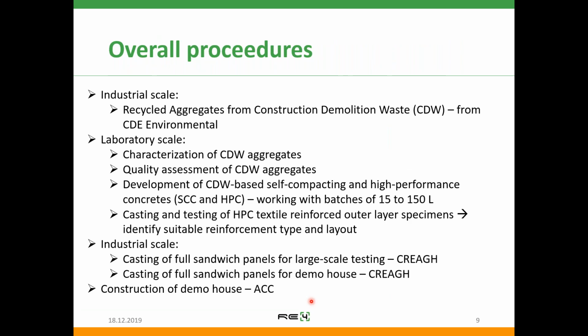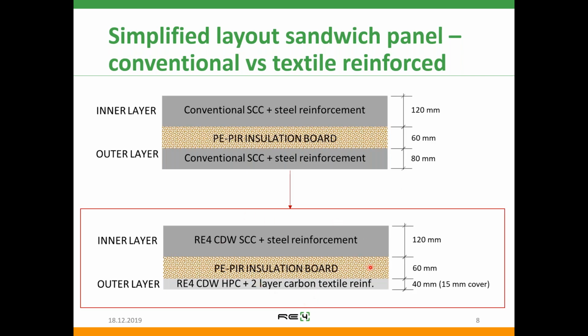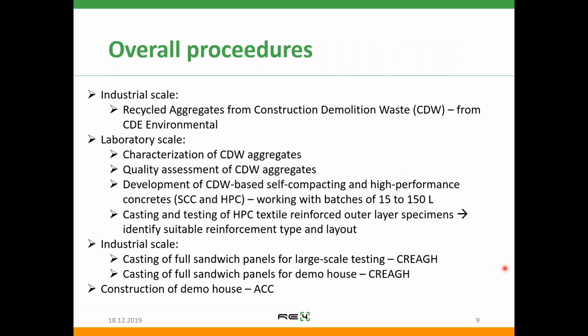And to say something about how you actually achieve this, because this is of course the end result of what we have achieved in upscaling, but it has of course been some work to get there. We started on industrial scale with the partner I mentioned, CDE, who provided the CDW. Then, of course, there is work in the laboratory where you need to characterize and quality assess the CDW for use as concrete aggregate. Then you need to adjust your mix design for your concrete mixes with replacement of CDW. And in our case, before going to upscaling at CREAGH, we also wanted to test different textile reinforcements to be in the outer layer to decide which type of reinforcement to go for.